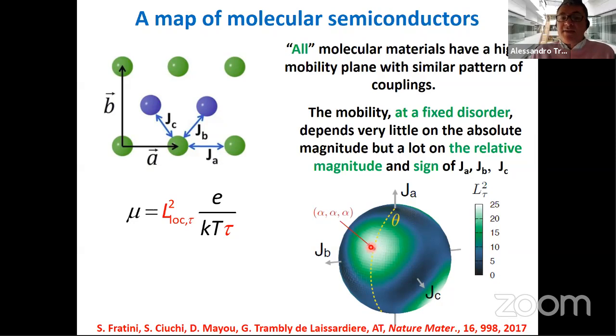And so there are interesting results. Let's say there are trivial results, for example, that one-dimensional materials are not very good for mobility and that isotropic materials are much better. But also something totally unexpected, which is, for example, that if you change the sign of one of the couplings, you end up there. So if you change the sign of JA, the material is not good anymore. So this is a qualitative map, we thought, that could describe what you should do to have a good material.